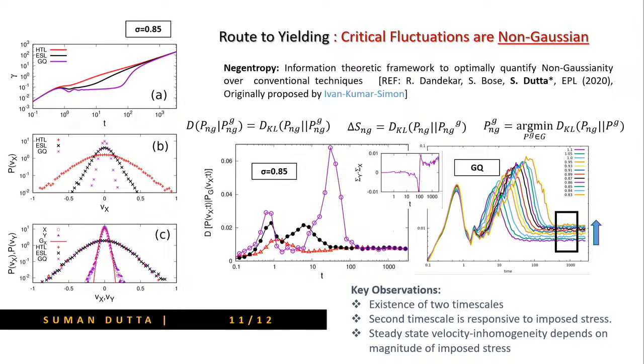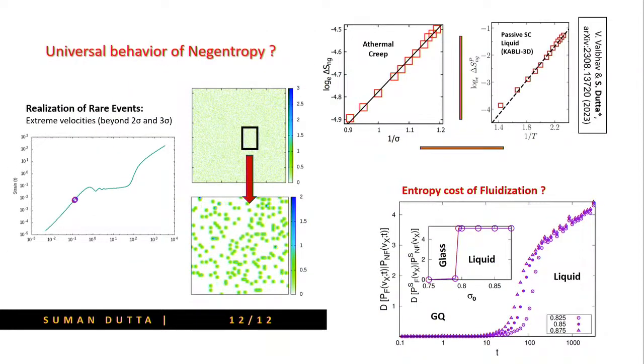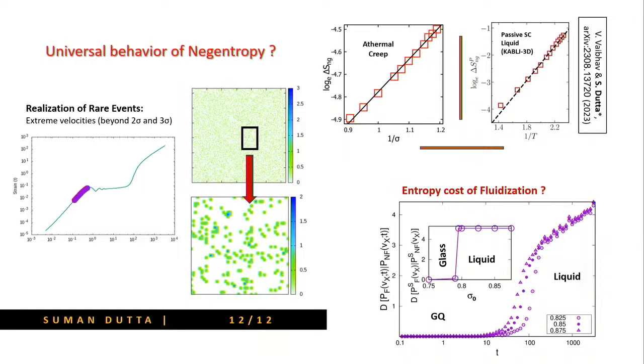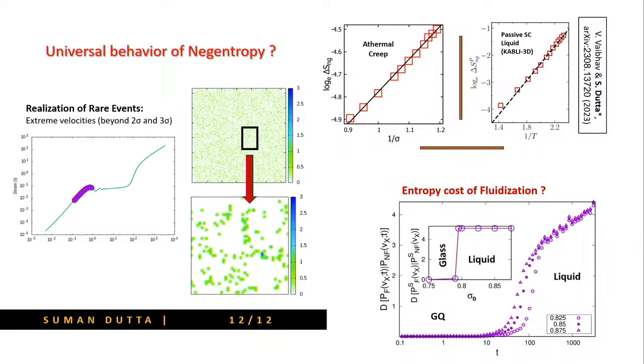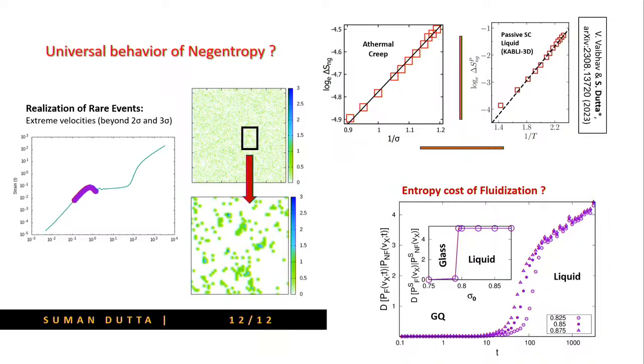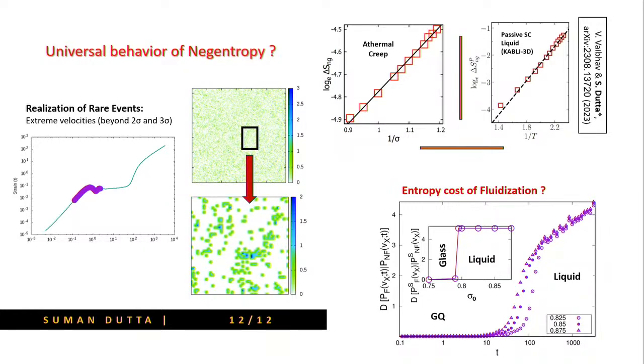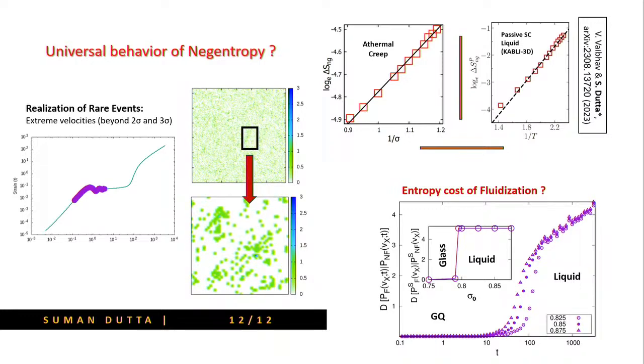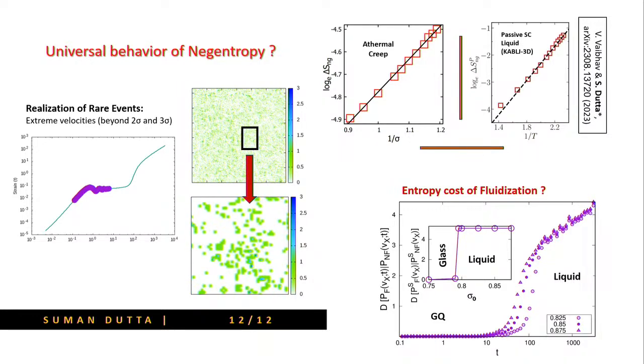The key observation of this investigation was that the 2 time scales exist. The second time scale is important, and it is responsive to the imposed stress. The third point was the steady state velocity inhomogeneity, which is dependent on the stress. This is the imposed stress value and this is the steady state non-Gaussianity, and that shows very surprising behavior. This log of delta S NG depends linearly on 1 by sigma.